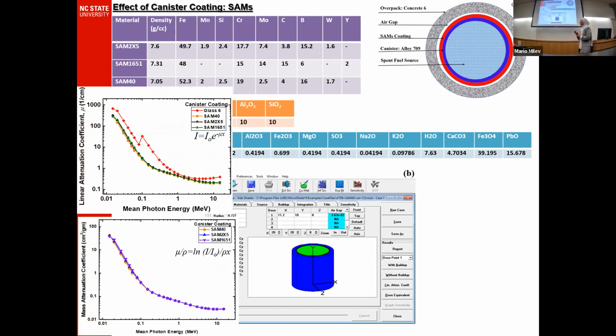So when we look at linear mass attenuation coefficient, we observe that the SAM material that includes molybdenum and boron exhibits high attenuation at lower energy, but the SAM which is X5, that has higher density and includes silicon and manganese, exhibits better attenuation at higher energies. When we compare it to glass 6, glass still exhibits better attenuation than SAMs. But what makes SAMs interesting is that they have better mechanical properties than glass 6 or glass-based coating, which makes them interesting to study as canister coating.